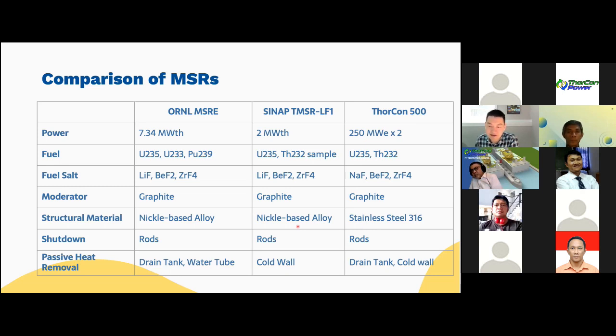Another reason is that the nickel-based alloy has this neutron embrittlement issue. That issue can be mitigated by developing new alloy, but stainless steel in general has better resistance to the neutron irradiation. Of course, there's always a catch that comes with the benefit. For stainless steel, the chemistry control of the salt needs to be maintained to mitigate the corrosion.